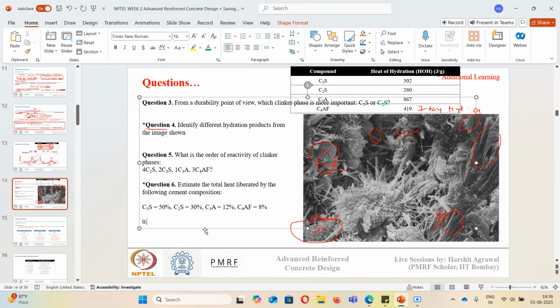So for C3S, it will be 0.5 times 502, plus 0.3 times 260, since C2S liberates 260 joules of heat per gram, then plus 0.12 times 867 plus 0.08 times 419. Like this we can calculate the total heat liberated by a cement if we know its chemical composition. So you can do this calculation and you will get the answer. I will do the calculation once to give you the value.